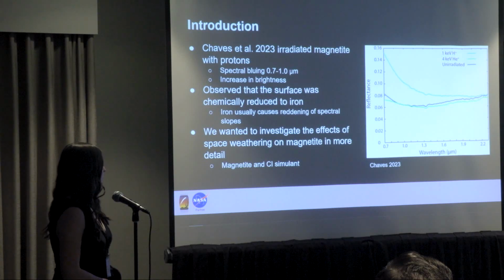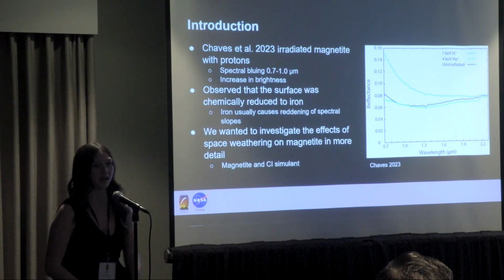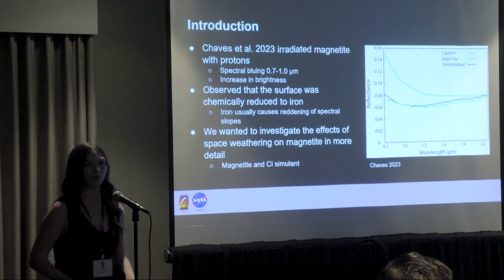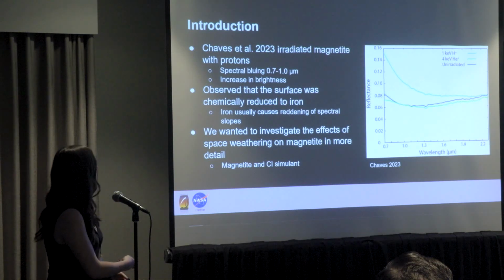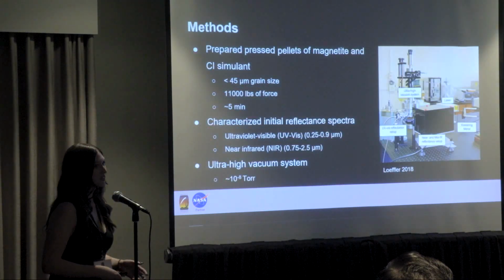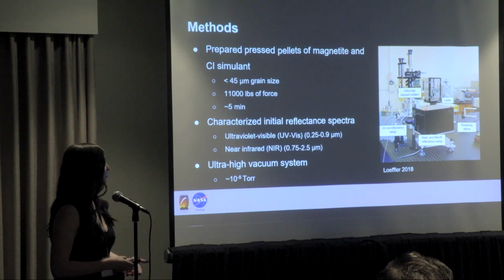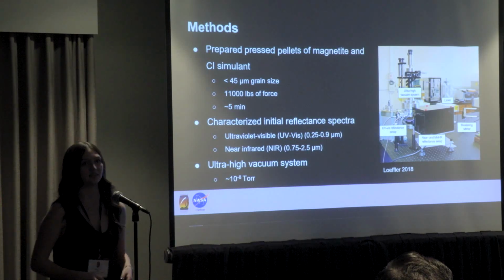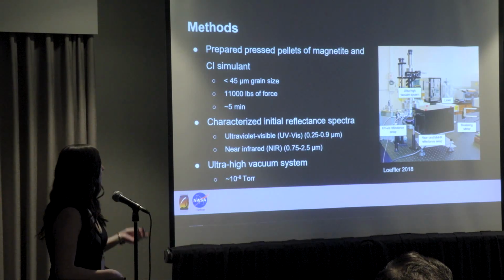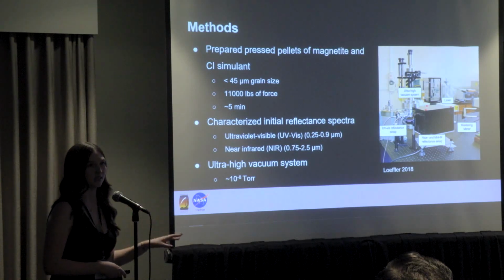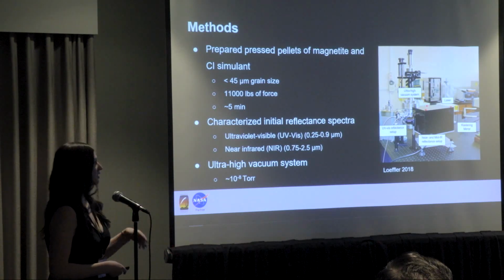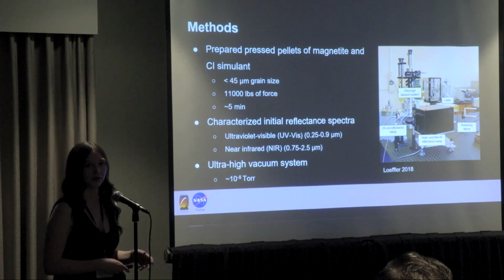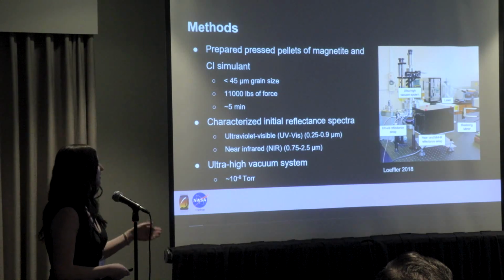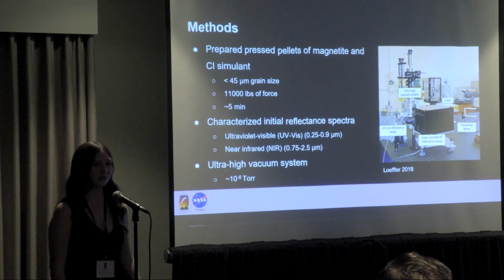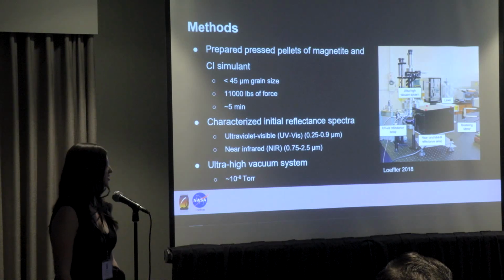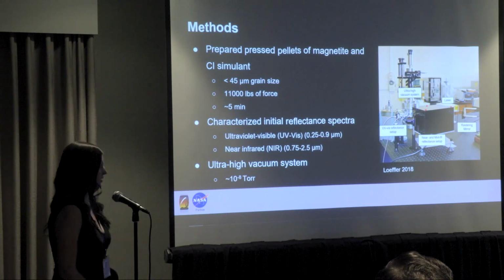So we chose to do studies on both magnetite and CI simulant because they're both important components of asteroids. So to do this, I prepared pressed samples of both the magnetite and CI simulant. And then before I did anything, I characterized the initial reflectance spectra in the ultraviolet visible and near infrared ranges. And then I put these samples into our ultra-high vacuum system, which gets down to pressures of about 10 to the -8 torr.